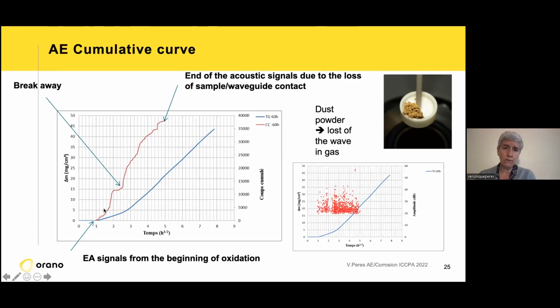the mass gain, and in red here you have the cumulative signal of acoustic emission. And you can see that in this case also, like the previous composite, you have the burst directly at the beginning of the experiment. You can also see here a strange effect: after a certain time, after 5 hours, you don't have any acoustic emission signal. Why? This is the same in this graph.